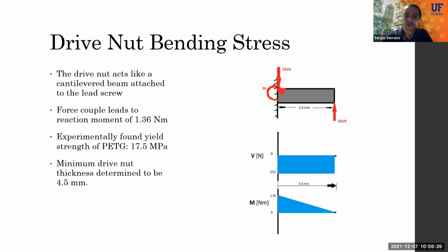Now onto the drive nut bending stress failure. If we assume that the drive nut is perfectly rectangular and only the points of contact with the plunger and the lead screw are relevant, then the free body diagram looks like the cantilever beam figured on the top right. Furthermore, shear force and bending moment diagrams were used to determine the bending moment and stresses. The minimum drive nut thickness was determined to be 4.5 millimeters. Anything less would likely lead to failure from bending stress. As a result of this analysis, the thickness was increased to 11 millimeters, leading to a factor of safety of about 2.4.